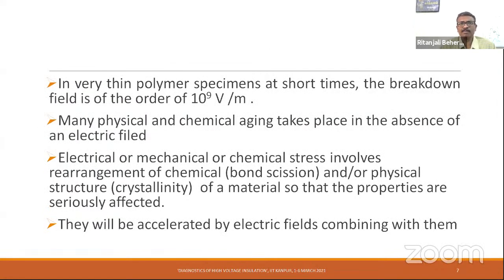In very thin film polymer specimens at short times, the breakdown field will be in the order of 10 power 9 volts per meter. However, there are many physical and chemical aging processes that take place in the absence of electrical field. Those chemical changes could be bond scission, and the physical structure such as crystallinity also will be altered. Under the influence of electric field, or even without the influence of electric field, both can take place. Now, the presence of electric fields would accelerate those degradation mechanisms.